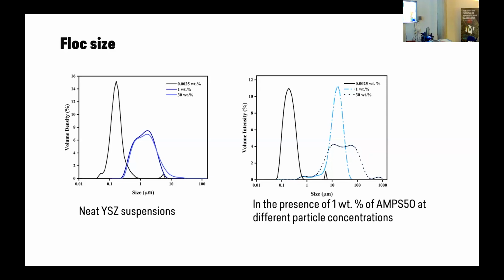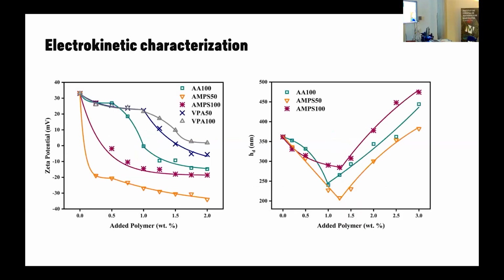And we do these experiments with the best polymer. We choose the best polymer that we would like to work with, and we constantly increase the amount of the particles in order to see the flock formation behavior. So here, you see this AMPS 50 polymer, 50% acrylic acid, 50% AMPS, is actually giving us the best behavior. Also, in zeta potential, that polymer itself, AMPS 50, lowered the zeta potential better than the others. And here, it managed to decrease the hydrodynamic radius better than others. So that is why we have chosen it.